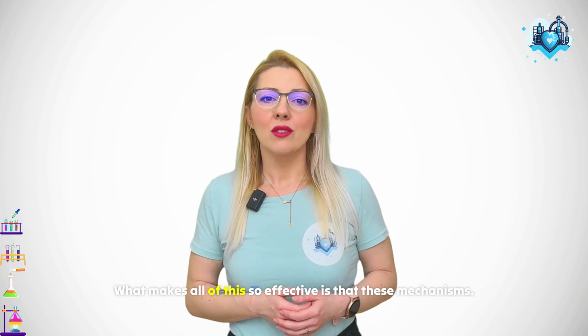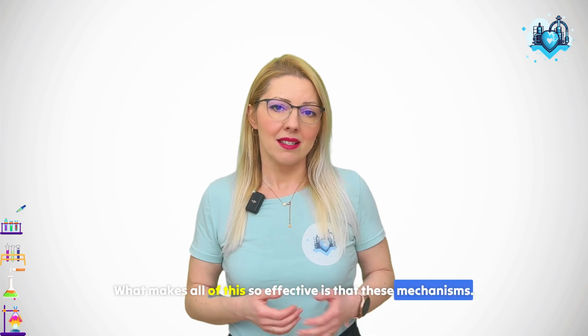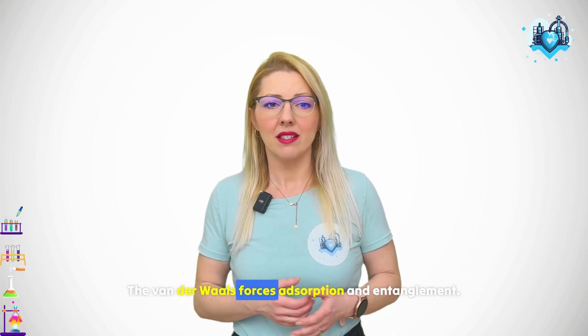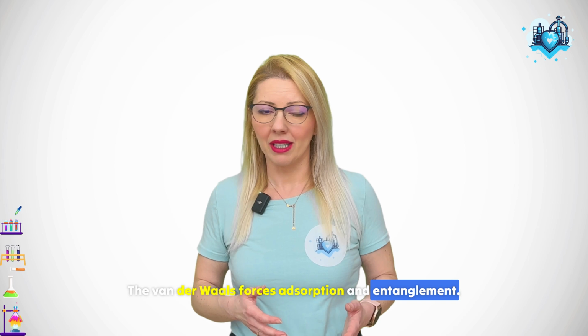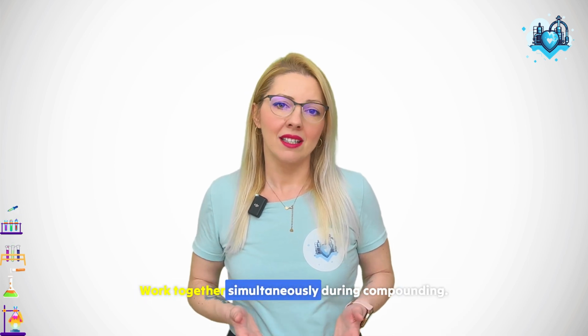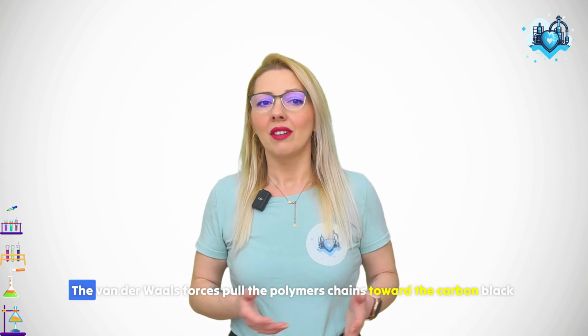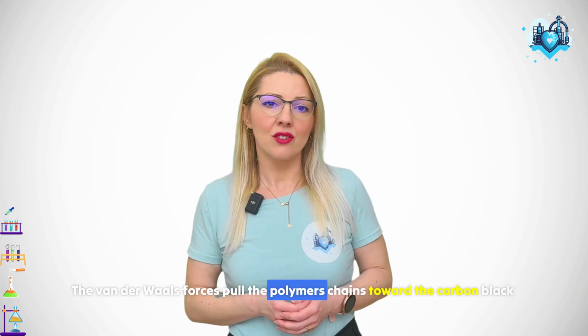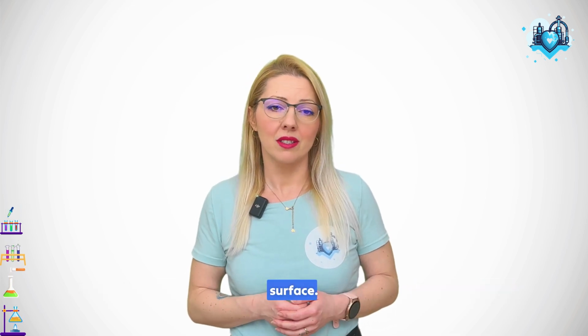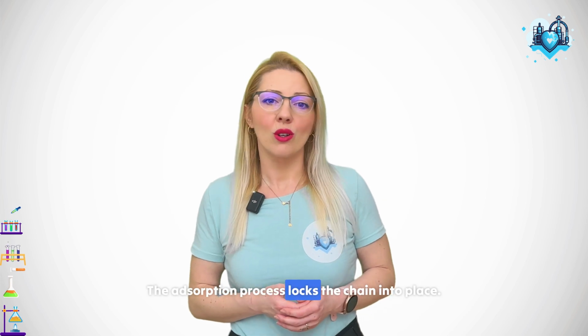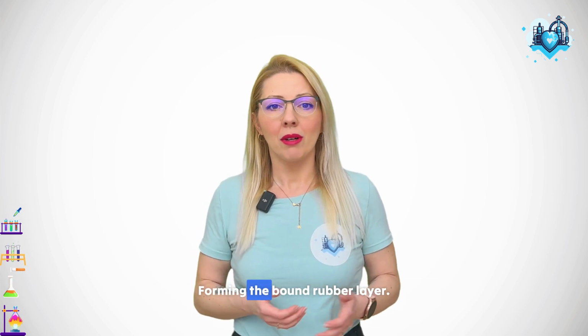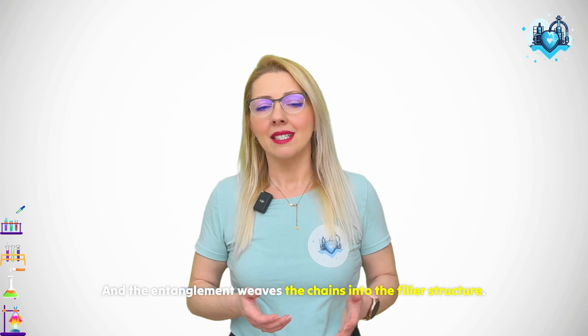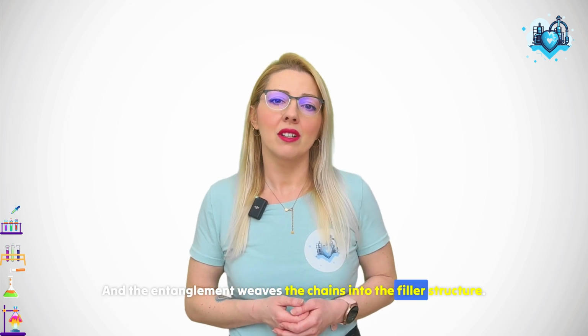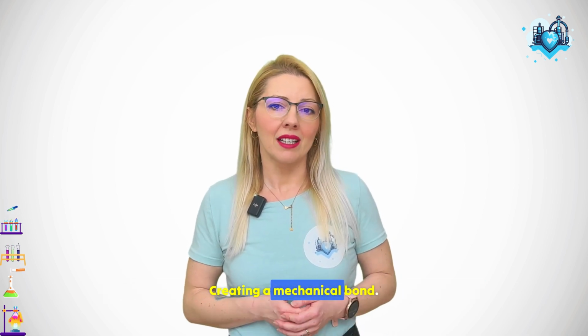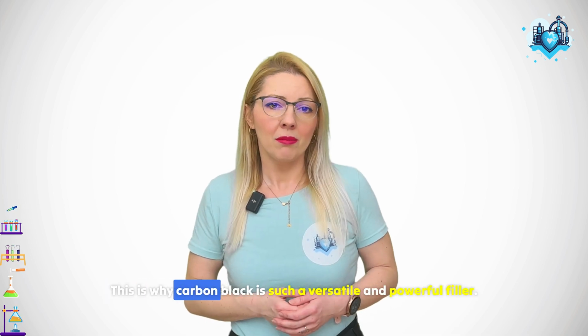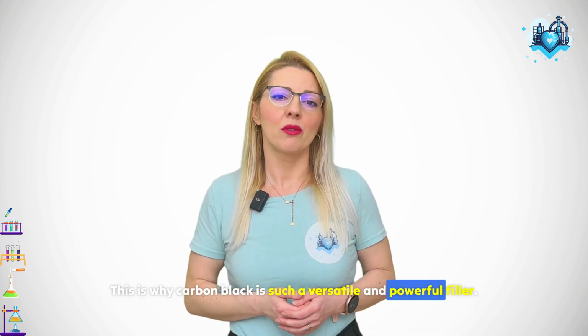What makes all of this so effective is that these mechanisms, the van der Waals forces, adsorption, and entanglement, work together simultaneously during compounding. The van der Waals forces pull the polymer chains toward the carbon black surface. The adsorption process locks the chain into place, forming the bound rubber layer, and the entanglement weaves the chains into the filler structure, creating a mechanical bond. This is why carbon black is such a versatile and powerful filler.